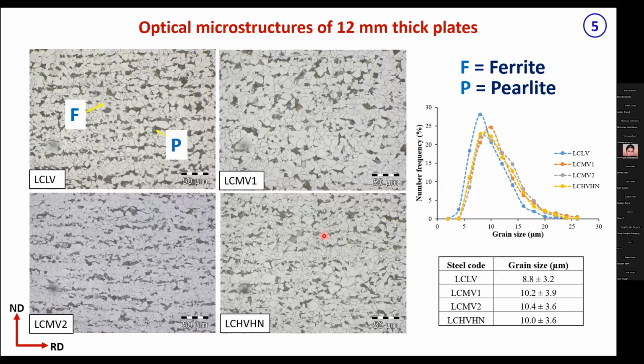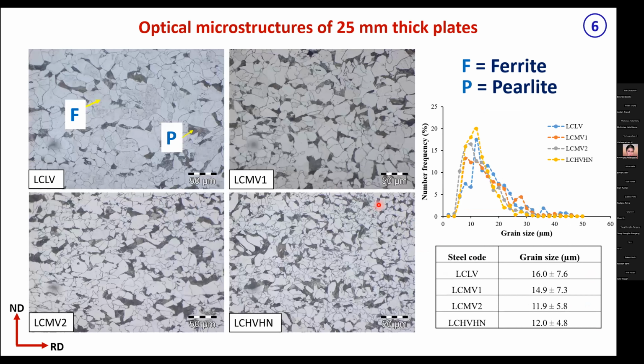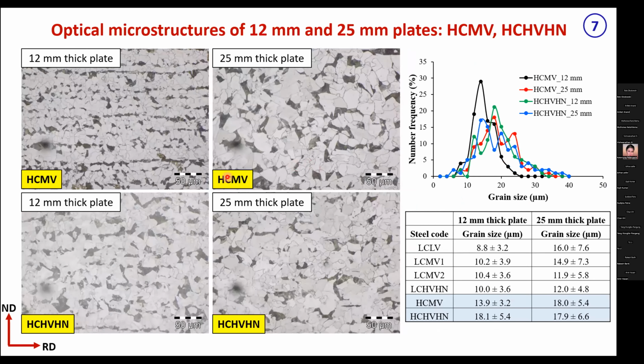These are the microstructures that I presented in the last meeting, which were rather good, quite fine microstructure with ferrite grain size in the range of 8 to 10. So the previous slide was for the 12 mm plate, this slide was for the 25 mm plate, where the grain size was a little higher, of course, because of the larger thickness and lesser rolling reduction. This time, one issue happened with us that our grain size was relatively higher. You can see 13 and 18 in that range.